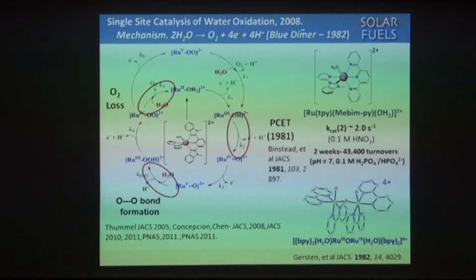The first example of a designed water oxidation catalyst was this one. Notice there are 2 bipyridines, 2 rutheniums in this case, an oxo bridge, and 2 waters. The key to this in the end is that you have to have a water in the coordination sphere at some point to do water oxidation, perhaps not a big surprise. This first observation was back in 1982. This field has evolved very quickly, especially of late.